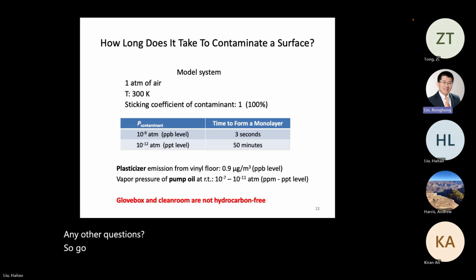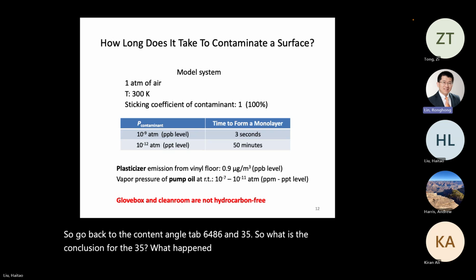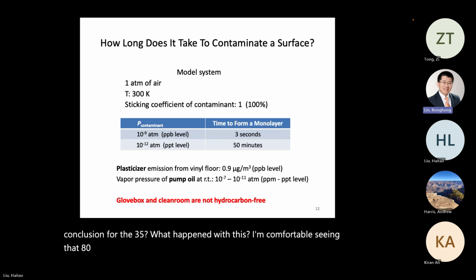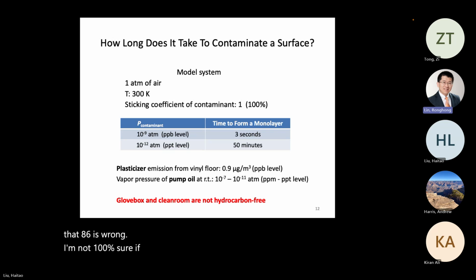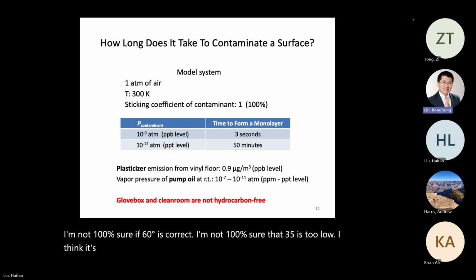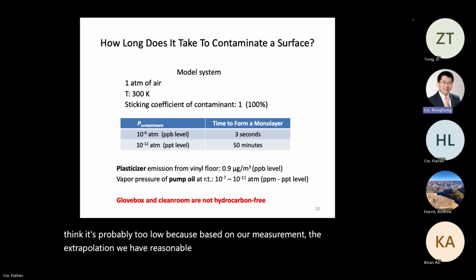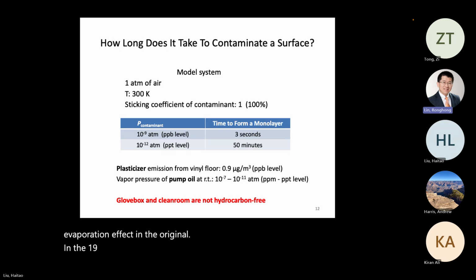So go back to the contact angle. You have 64, 86, and 35. So what is the conclusion for the 35? What happened with it? I'm comfortable saying that 86 is wrong. I'm not 100% sure if 60 degree is correct. I'm not 100% sure that 35 is too low. I think it's probably too low because based on our measurements, the extrapolation, we have reasonable confidence to say that even if you do extrapolation, it's not going to go to 35. So there might be a water evaporation effect in the original 1978 experiment.